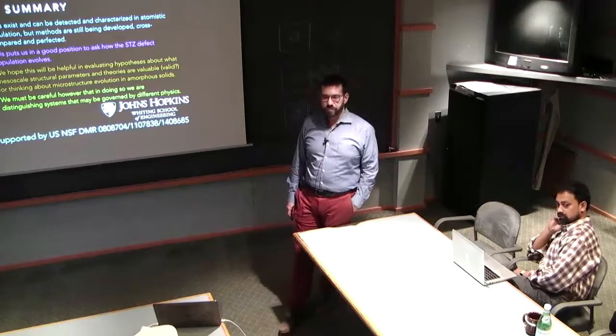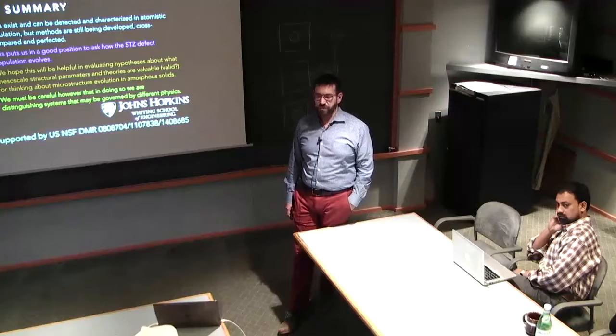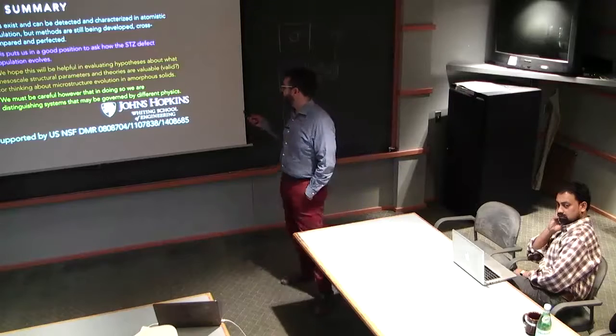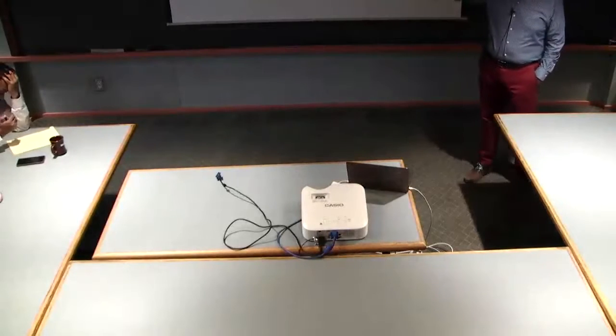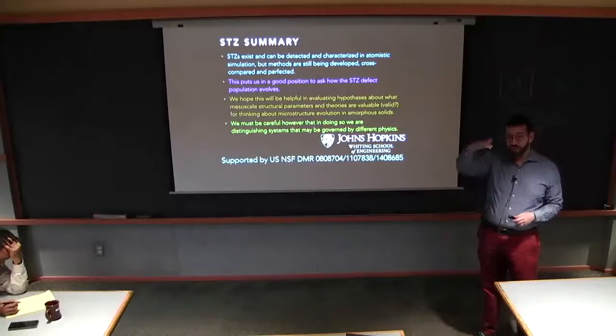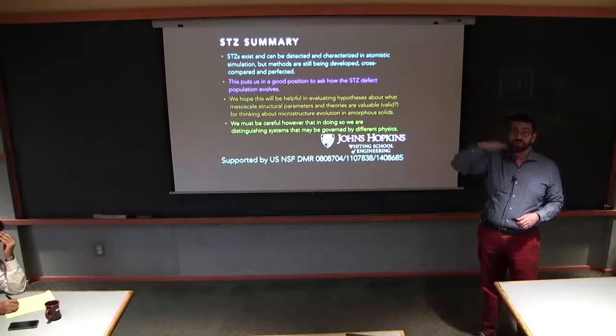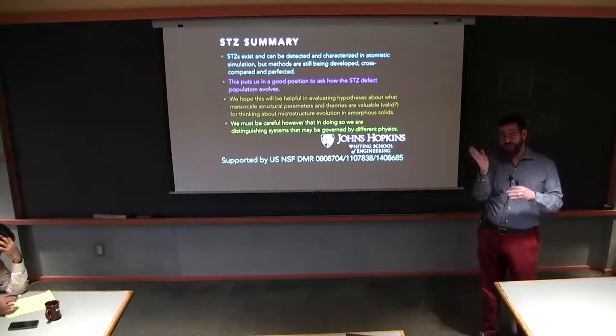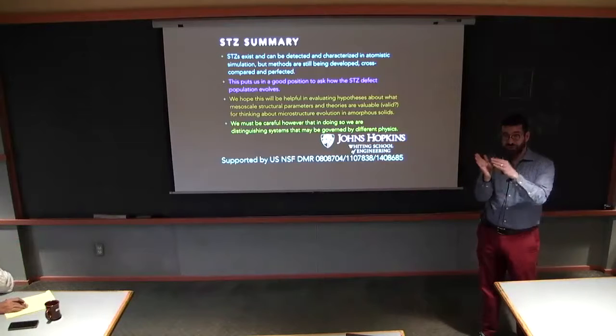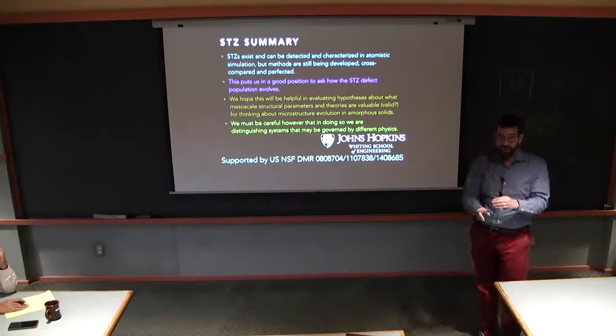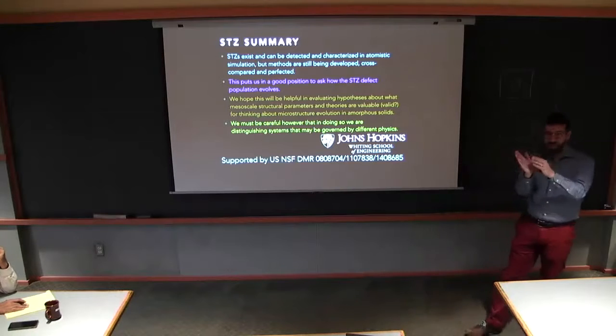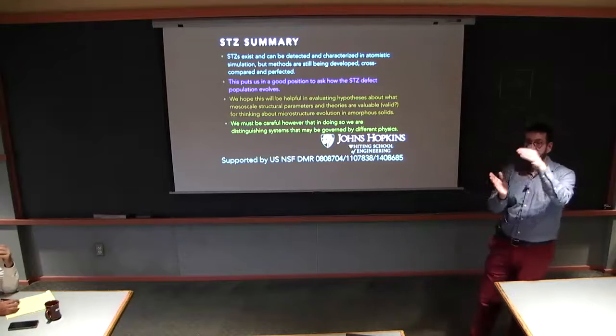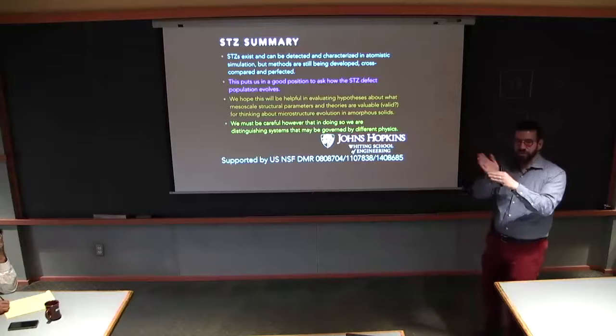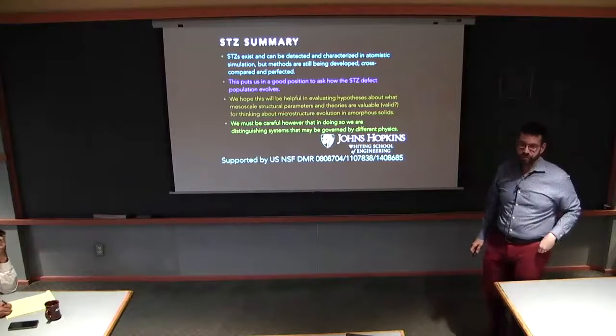You had this orientational dependence on where you found these local soft places. Did that play out when you sheared the bulk? Yes. In fact, to do the quantitative correlation, we specifically looked not just at the low local thresholds, but the resolved stress along the direction of the applied shear stress relative to the local yield direction. It's similar to the Schmid effect on dislocation motion if you're familiar with dislocations—basically the resolved tensor along the applied shear direction, because they have an orientational dependence.